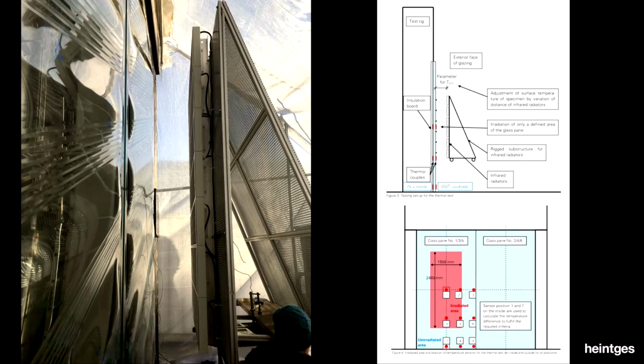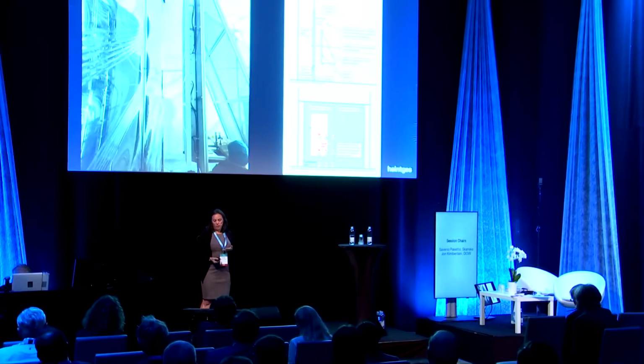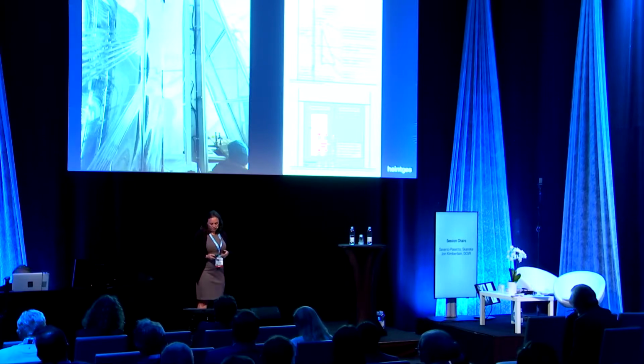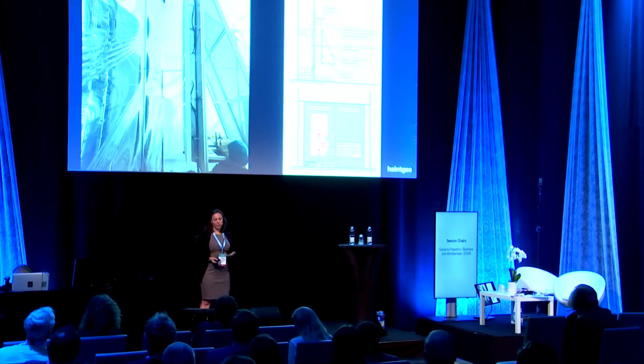This is the test setup for a thermal stress test, where a heat source was put in the middle of the glass, and we looked at the temperature differential across the glass. Based on calculations, the expected differential between edge and center of glass was about 20 degrees Celsius. The idea was to test to 2 times that, and then also to try to test to breakage. However, even achieving a 120 degree differential between the cold edge and the warm center, which was as high as the equipment could get, there was no breakage. So that gave everyone another level of comfort with the thermal stress.